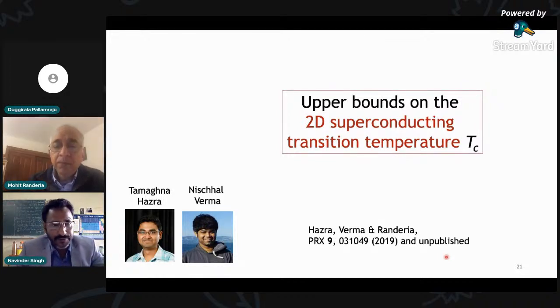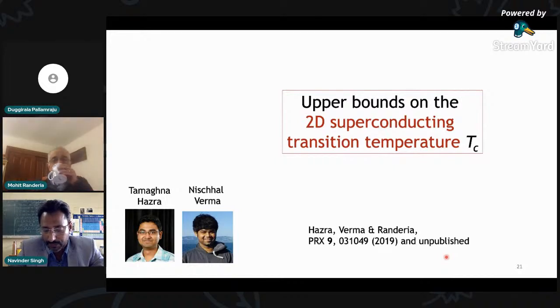Yeah, but if possible, maybe I would like to ask one question. Please. Yeah, so this is related to the upper limit of Tc. So there was an argument by Anderson and Cohen, based on the divergence of the dielectric function, that they argued that the Tc cannot be more than 30 Kelvin roughly, or 30-40 Kelvin. Yeah, but that argument is just completely wrong, because we know many.